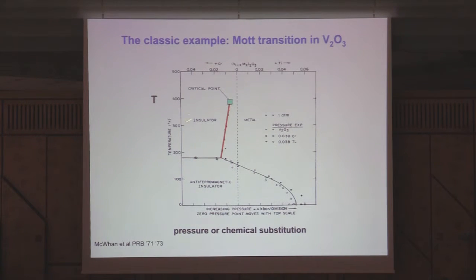And I want to make clear that it's not this insulator, which is an antiferromagnetic insulator. The Mott insulator is an insulator we really do not expect to be one, because there is no long-range order. In the presence of long-range order, of course, you can change the bands and change the lattice periodicity and get insulators. But here you have a paramagnetic insulator. Moreover, as was emphasized before, you can go from this insulating state to this metallic state, above in temperature, changing the pressure, in a totally continuous fashion, and you have a first-order line that ends in a second-order critical point, like in the water-vapor transition.